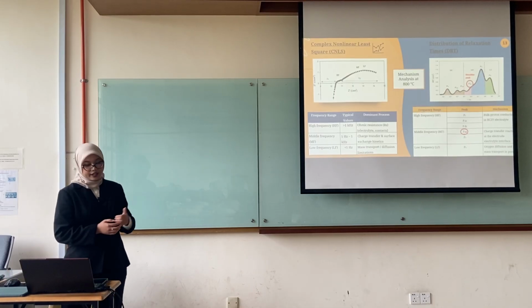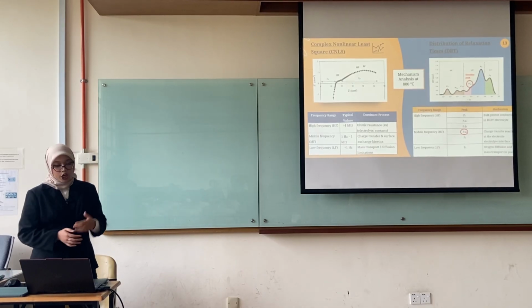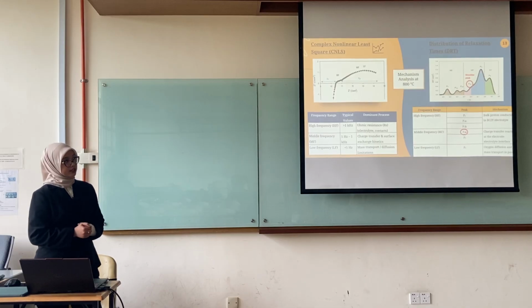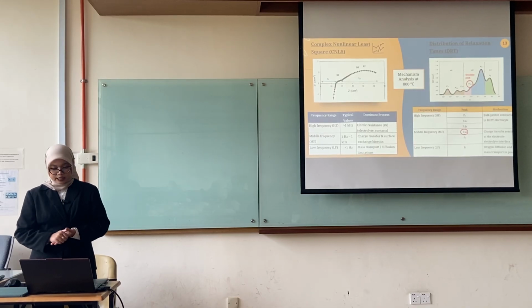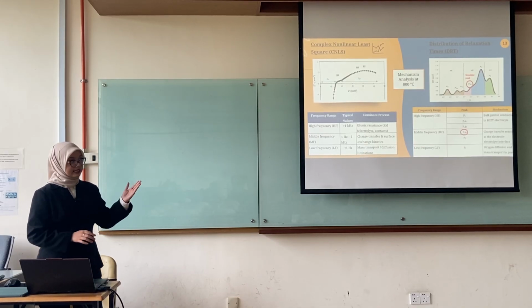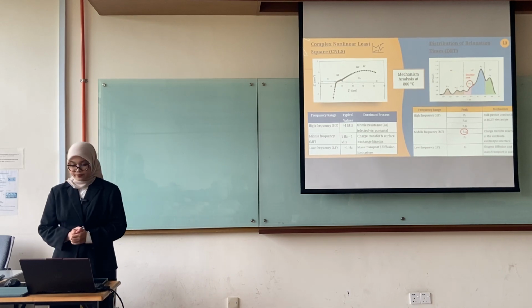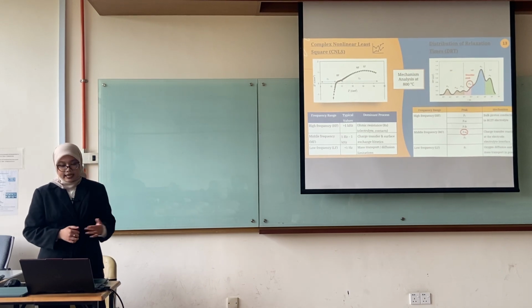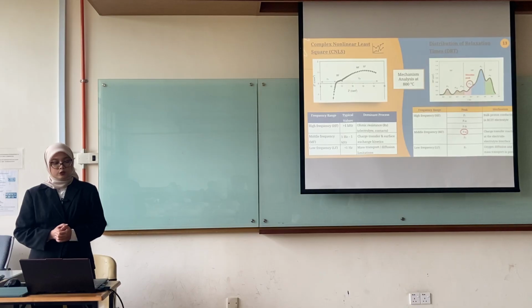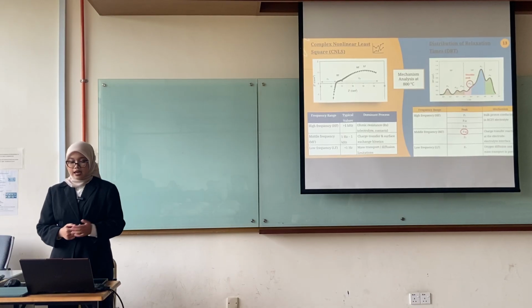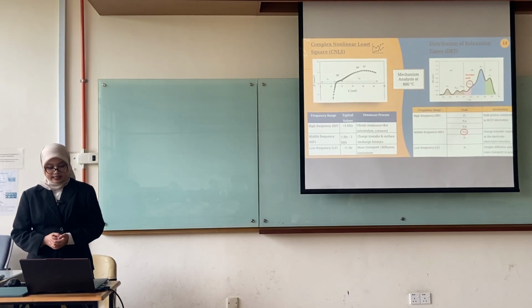So at 800 degrees Celsius, DRT confirms proton conduction, charge transfer, and oxygen diffusion as distinct contributions, making it a more powerful tool for mechanistic analysis.